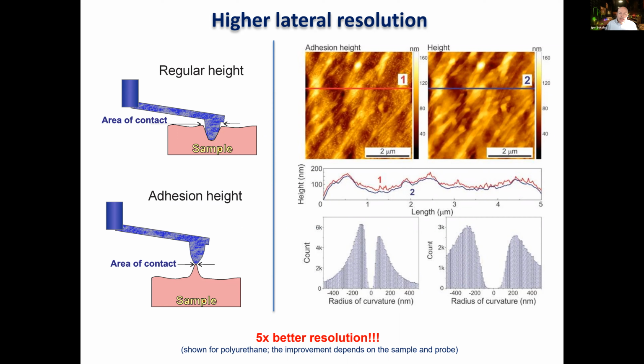In that case, it's simply because we don't need to average our data. For example, to get one pixel you need to average at least two taps, because the feedback works on the maximum load force, the peak force. The first time you get whatever you measure, but you need to correct the feedback, so the next one will be the correct one. So minimum two. But again, feedback doesn't work instantly, so it's better three or four. That's why it slows down.